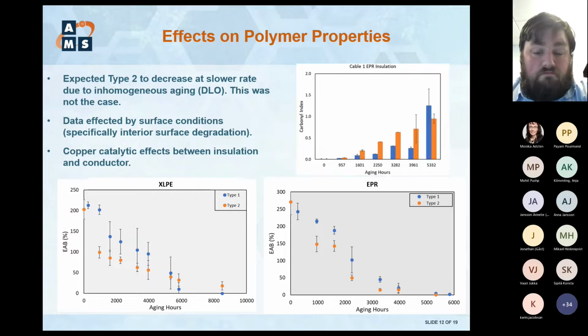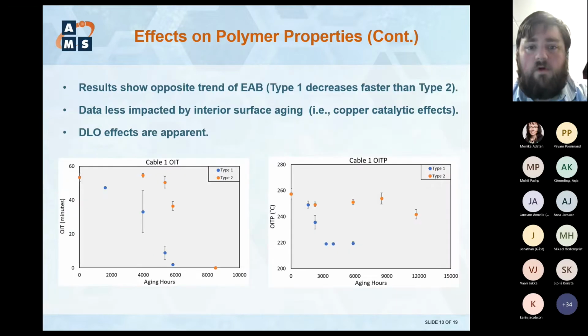Basically, what actually happened is the type 2s decreased faster or at the same rate, essentially, EAB wise, as the type 1s. The reason for that, after doing analysis, we think is because of the copper catalytic effects that are going on, the surface effects that are going on. So EAB is generally really affected by surface oxidation. It's a technique that is very affected by surface conditions because of that copper catalytic effect and the surface reactions going on. We did not see the DLO effects we were thinking we would see. We actually saw basically the opposite. Type 2s decrease faster than type 1s.